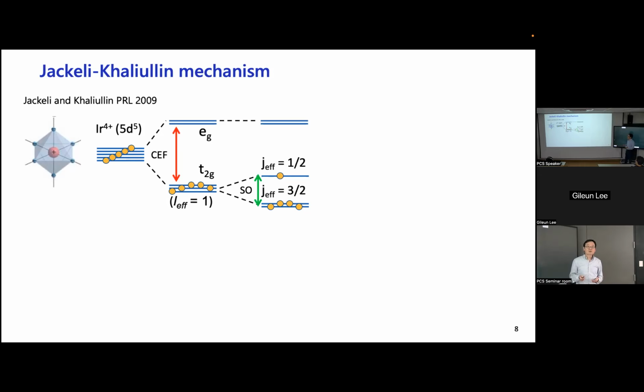And so this kind of solution was provided by this idea by Jackeli and Khaliullin. If we start with a very strong spin-orbit coupled material like iridates or other very heavy transition metal elements, with 5d electrons, and you turn on the crystal field levels and spin-orbit coupling and so on, and you do all this kind of chemical massaging, then you end up with the ground state of J effective equal to 1/2 state, or sometimes called Kramers doublet state.